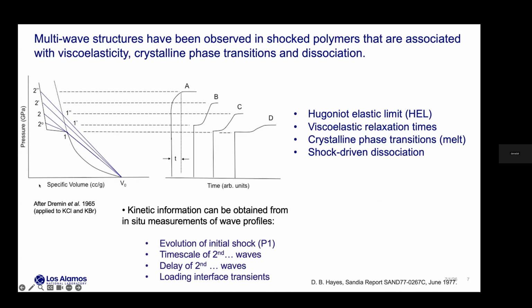So the diagram on the left is pressure-specific volume. You've got here a Hugoniot for the first state, and then you've got a Hugoniot associated with the second state. And this could either be a solid-solid phase transition, or it could be a densification transition, such as decomposition. But as you shock into this manifold of states, you're going to get a variety of different profiles. So if you shock just in a phase space where you're only accessing the first state, you would get a single wave. But as you get into this regime where you start to see these evolutions between structures, you start to get these multi-wave structures. And so these are similar in many ways to detonation waves, but they're associated with densification transitions instead of expansion or volume expanding transitions.